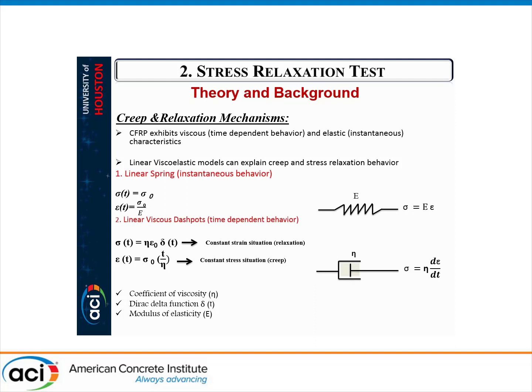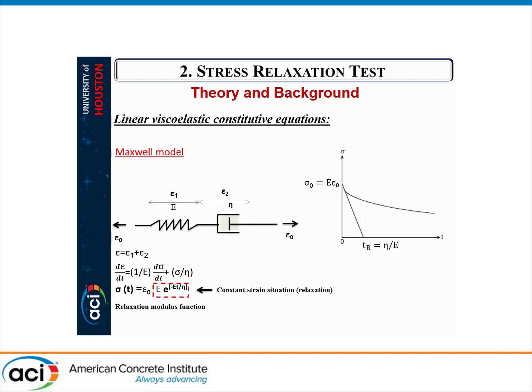In general, creep and relaxation mechanisms can be explained through the theory of viscoelasticity. Several viscoelastic models were previously developed to explain the relaxation phenomena. What is common among all these models? We have a linear spring to represent the instantaneous behavior, and we have a linear dashpot in the model to represent the viscous or long-term behavior. One of the very basic models for representing the relaxation in the CFRP composite is the Maxwell model, which includes a linear spring and a linear dashpot in series configuration as presented in this figure. By applying a constant strain to the system, the time-dependent stress can be obtained as an exponential function of time, as presented in this equation and also plotted on the figure.